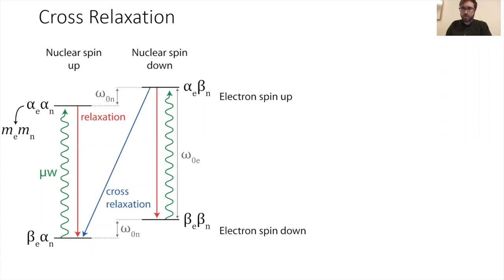Right, and next one on our list, and it seems that we are gaining more, which is excellent as time goes on. Why is the T1e of the lithium metal temperature independent? This comes from the mechanism, I guess, obviously. So electron relaxation in lithium seems to be dominated by scattering with impurities. And so you can make the electron relaxation longer and longer by just getting more and more pure lithium. And there are some interesting old ESR papers where they show that. Other metals have other mechanisms, in particular, when spin-orbit coupling is driving relaxation, that's temperature dependent. Whereas in lithium, perhaps because it's so early in the periodic table, the spin-orbit coupling doesn't play a role, and it seems to be dominated by scattering with impurities.